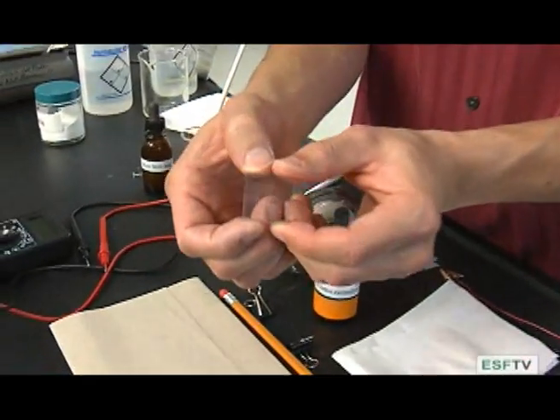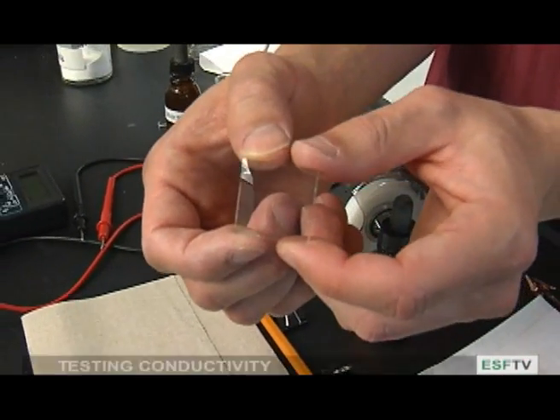You can see now that we have a smooth paste with no lumps. It's a little thicker than water but thinner than paste, more like the consistency of white paint. After we have the paste, we need to make a border on our glass so we can apply the paste. We're going to start with a piece of indium-doped tin oxide glass. This looks like normal glass but it actually has a conductive coating on it.